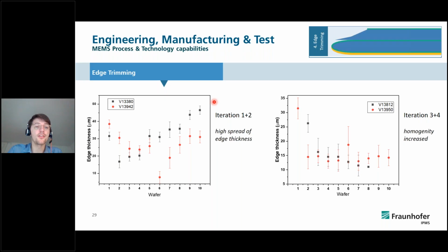And the homogeneity is not good enough from our perspective, so we tried to get some iterations done to improve the spread of the edge trimming. So we wanted to achieve actually 15 microns, and what we get here, you can see there were only 1 or 2 wafers that managed this, and sometimes we came up with 40 and more, and then we iterated again, and then we see that we are almost at the 15 microns thickness of the trimmed edge.